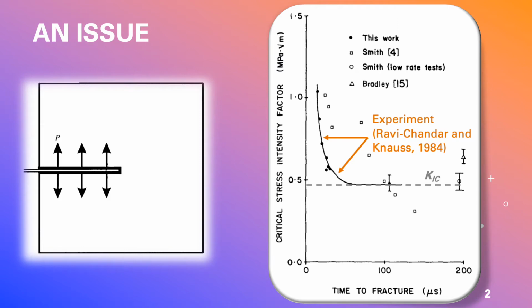At the end of the last century, Ravichandar and Knauss conducted a series of experiments on the dynamic crack initiation, its propagation and crack arrest in the brittle samples made of a glassy polymer material, Homalite 100. In their experiments on initiation of the crack growth, trapezoidal pressure pulses of various amplitudes were applied to the crack surfaces with a very short rise duration of 25 microseconds. Depending on the amplitude of the applied loads, the time after which the crack growth started varied. The higher the amplitude, the earlier the crack growth was initiated.